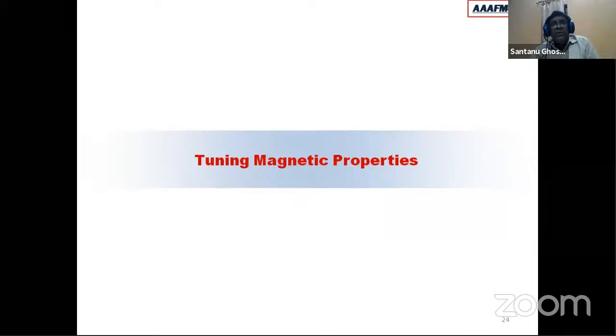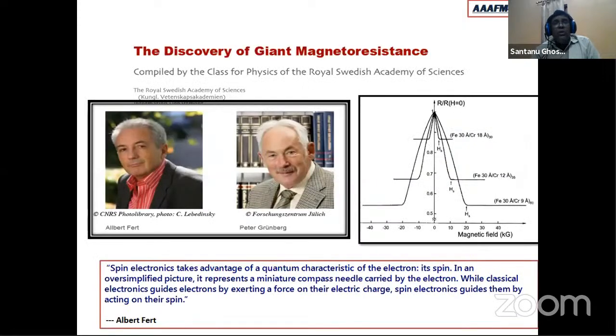Now the second part is the tuning of magnetic properties. So we all know that there is a big discovery, which is giant magnetoresistance, and Professor Fert and Professor Peter Grünberg discovered this giant magnetoresistance, where one can see very high resistance at zero field, which eventually falls with higher field, and the material system which they used was metallic multilayers.